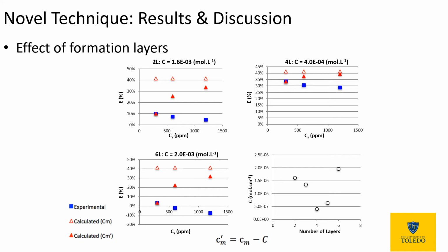To try to account for a potential cause of this, we decided to assume that a fraction of the free salt inside the membrane is not mobile, that this salt is split, that the anion and the cation are associated with the polymer that makes up the membrane structure, and therefore are not able to diffuse freely or to convect freely.